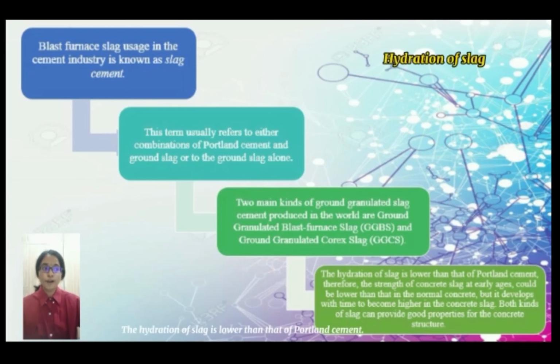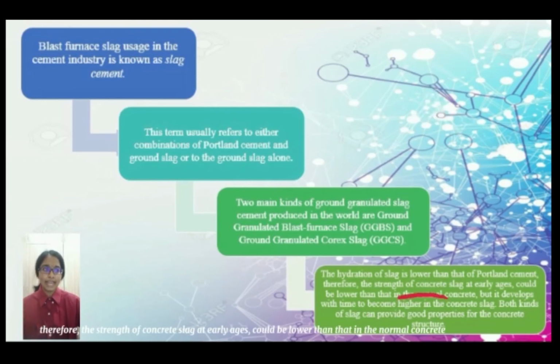The hydration of slag is lower than that of Portland cement. Therefore, the strength of slag concrete at early ages could be lower than that in normal concrete, but it develops with time to become higher in the slag concrete. Both kinds of slag can provide good properties for the concrete structure.